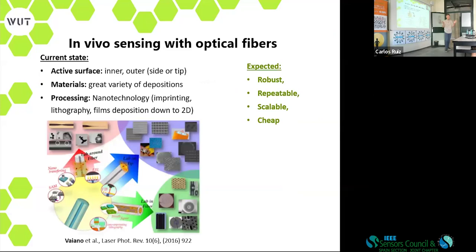Why? There were a lot of attempts, but none of them was really successful. And I believe that the main problem is the number of samples. For this biosensing experiment, we need a large number of samples, possibly very similar, not different. And the methods proposed to date are very complex. One of them is to make some patterning of the surface of the tip of the fiber. It works, but not many times. It can be fabricated and shown as a principle, but mass fabrication is not possible. Some other processing of the fiber makes the fiber very fragile, so it probably would not work. Putting something inside the fiber, not really.